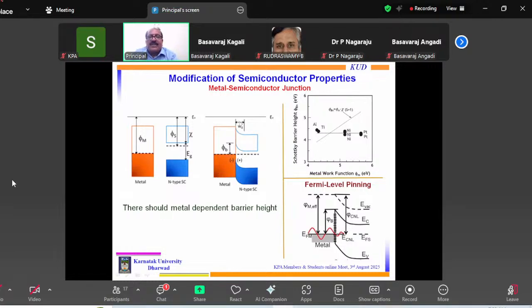This barrier height, what I showed you now, depends upon the contacting metal. If I change the contacting metal, I can choose metals having a different work function so that I can try to move them. If I do so, I should be able to vary the barrier height. Theoretically speaking, this is a very simple equation that predicts how barrier height varies with respect to the electron affinity of the semiconductor or the metal work function. What you see is that a theoretically predicted line should go here. As I change the metal, like gold and silver, I should be able to vary the barrier height.